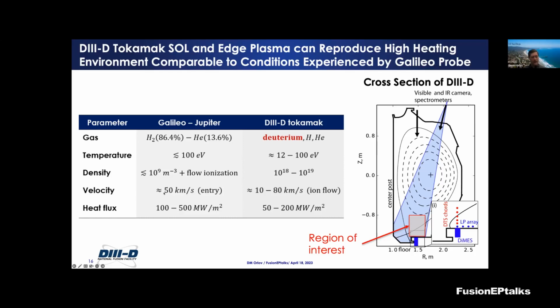The velocities, as I said, were about 50 kilometers a second when the probe entered Jupiter, and they're about 10 to 80 kilometers a second for the ion flow velocities in the DIII-D edge. And the heat flux values are very comparable: 100 to 500 megawatts per meter squared in Jupiter's entry, and 50 to 200 that we can probably get in the DIII-D tokamak.